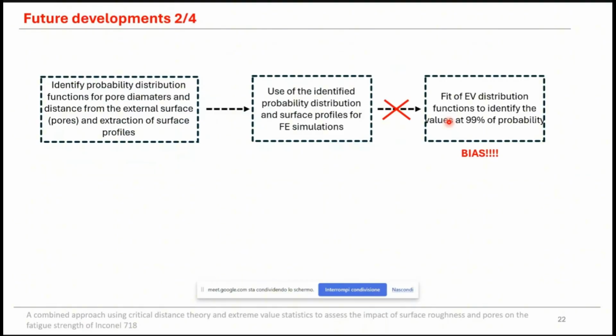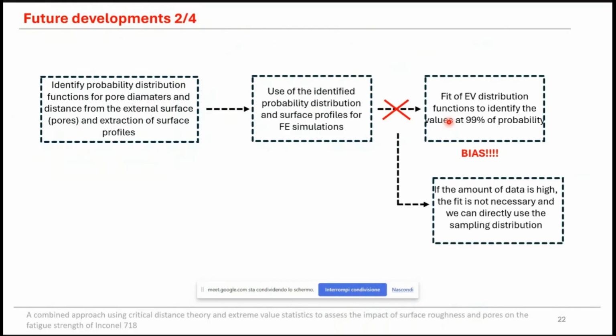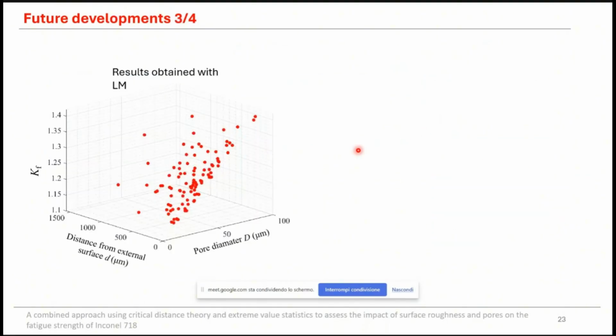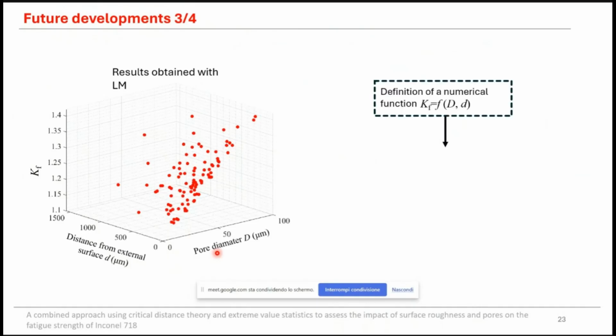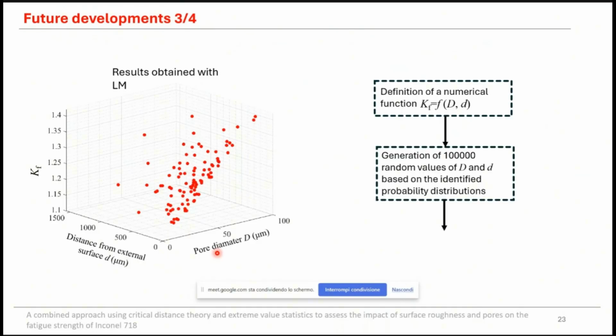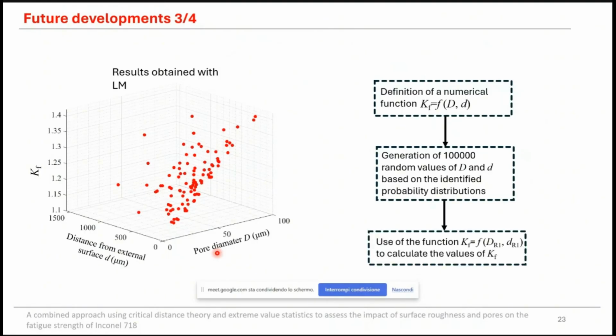Because in principle, if one can generate a very high amount of numerical data, we can directly use the sampling distribution. In fact, for further analysis, we built a numerical function to relate the fatigue stress concentration factors of the pore, according to the theory of critical distance, to the distance from the external surface and pore diameters, by simulating a set amount of data of approximately 100 or 150. And then we generated a very high amount of data of diameters and distance from the external surface through the probability distributions identified on the experimental data. The generated data were substituted into the obtained numerical function of the stress concentration factor.